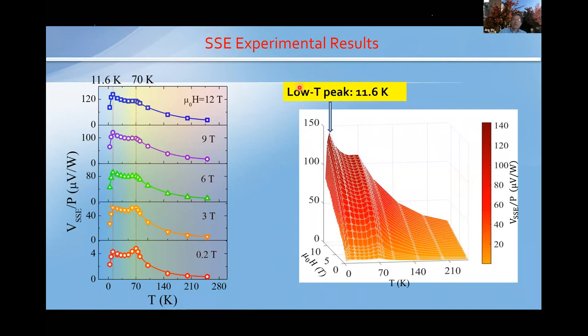So again, this low temperature peak is located around 12K also. This high temperature peak is located at around 70K, right? So essentially it's similar characteristics shown here for selected fields. Okay, so now let's look more carefully.